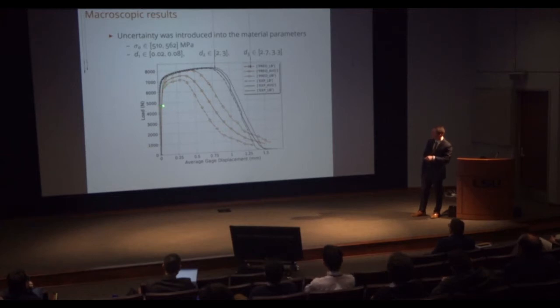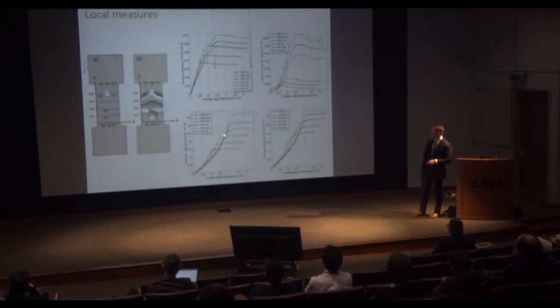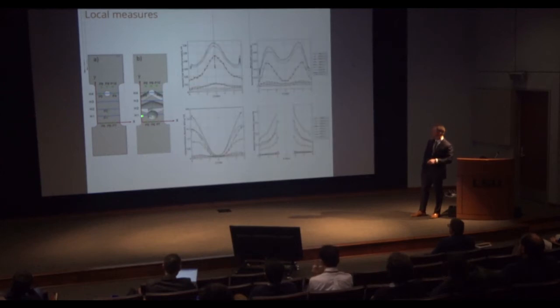In fact, we didn't even get the elastic modulus correct, which is a little concerning, because if you go back to the calibration model, the lines are right on top of one another, right? What happened? Here are some of the other measures, in this case the surface strains at those points. In all cases, we're a little bit low there. These are the strains along the vertical lines, the blue lines, so horizontal lines. Again, the black lines are the results of the experiments, and the red or orange lines are our predictions. And in all cases, when you look at the details, we did fairly poorly.